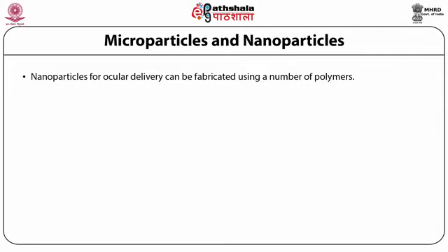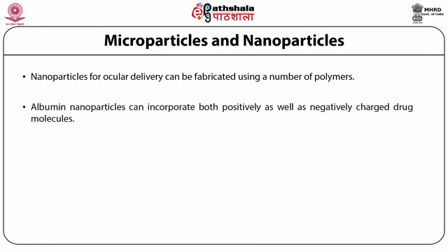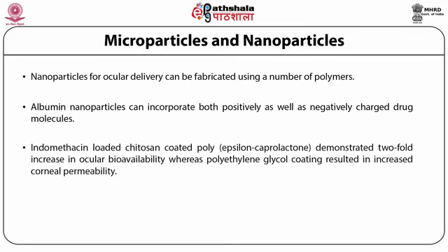Nanoparticles. Nanoparticles for ocular drug delivery can be fabricated using a number of polymers. Albumin nanoparticles can incorporate both positively as well as negatively charged drug molecules. Indomethacin-loaded chitosan-coated polycaprolactone demonstrated a two-fold increase in ocular bioavailability, whereas the polyethylene glycol coating resulted in increased corneal permeability.